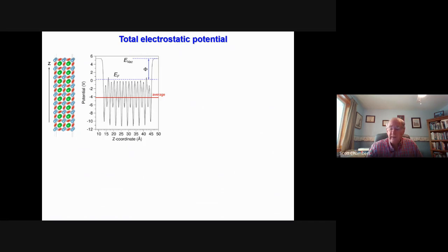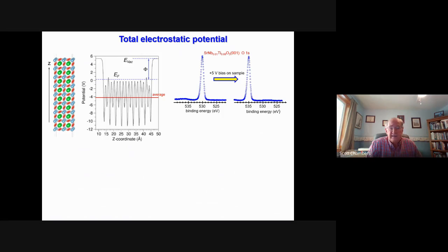And to illustrate this, let's take a semiconducting material or a metallic material, anything that doesn't charge up in photoemission. So we'll take the oxygen 1s on niobium doped strontium titanate, which is an N-type semiconductor. Okay, as properly grounded, you measure about 530 eV. Well, in my spectrometer, I can float the sample. I can put a bias on the sample. And so let's suppose I put a 5-volt bias on the sample. That moves all the peaks 5 eV higher in binding energy, or in this case, 5 eV lower in kinetic energy. And that's because I have now changed the electrostatic potential of the entire crystal, and the peaks move accordingly.